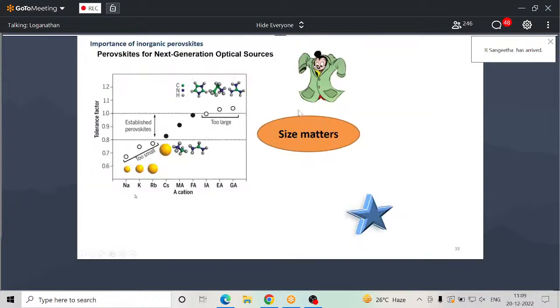And here, this is another schematic. Here you can see the importance of size: the tolerance factor and the A cation. If you change the A cation from sodium, potassium, rubidium, cesium, you can see how the tolerance factor is getting enhanced. So if we go up to cesium or MA or FA, their tolerance factor is nearly 0.8 to 1. So in that range, it can be very stable. If you go across this spectrum, then the stability is not that good because the ionic radius is getting higher, so your structure will get deformed. Eventually you'll end up with a much worse result. So you have to consider this kind of cationic system to build a perovskite molecule.